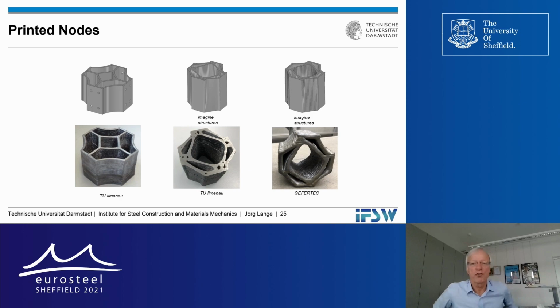And here we see 3 printed nodes that were printed by our research partners at the university in Ilmenau and by Gefertec, a 3D printing company in Berlin, in Germany. What's interesting is, if you look at the inside of these nodes, they always have a different geometry depending on the loads. On the left-hand side, we have 4 members coming with the same moment and the same normal forces, same shear forces, so you get a very symmetric structure.